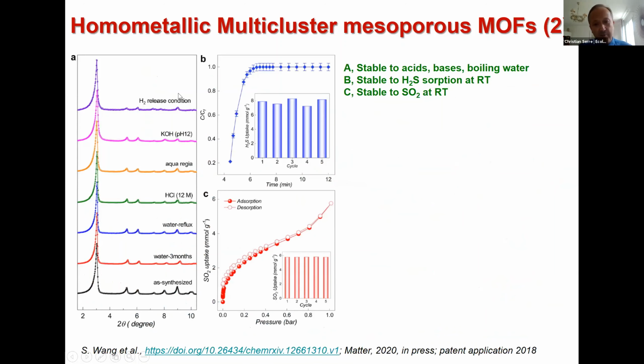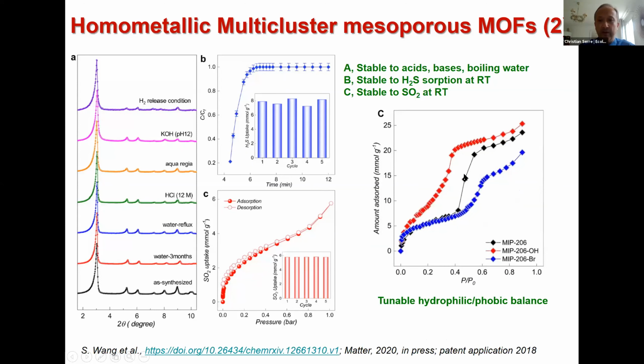And if you have large pore zirconium MOF, sometimes it's stable chemically, like NU-1000, sometimes it's not so stable, like UiO-67. Here we are lucky, it is very stable in acid, high temperature and so on, and also stable to acid gas: 5 cycles of absorption of H2S and SO2. And then you can tune the hydrophobic balance by changing the functional group, as you can see with the bromo, the non-functionalized, and then the OH functionalized material.